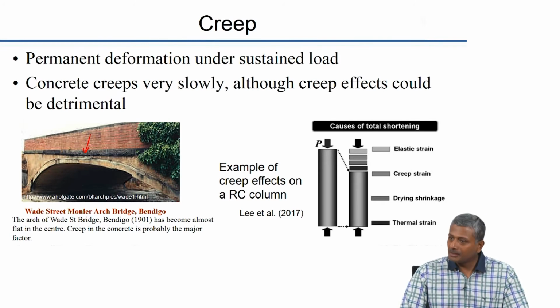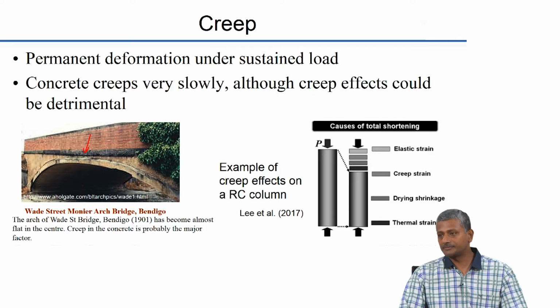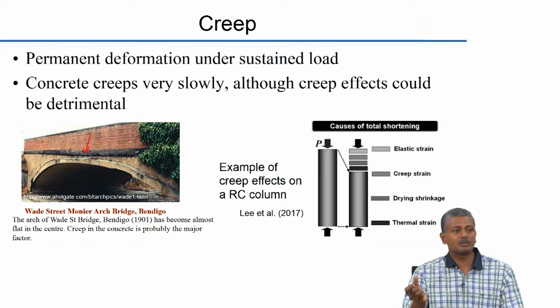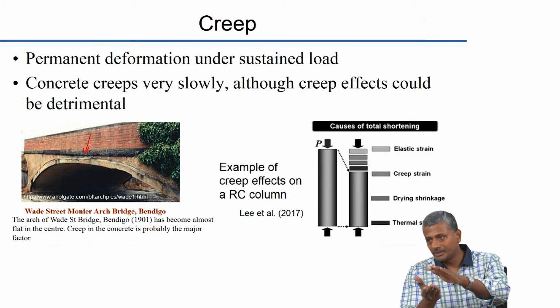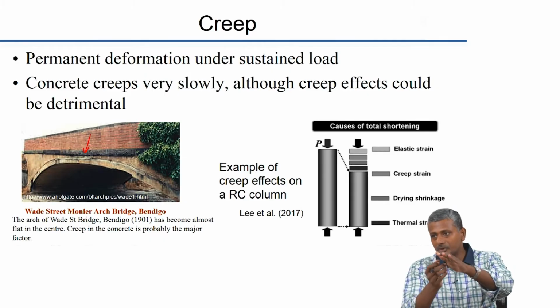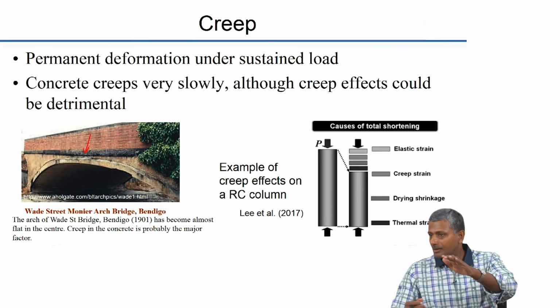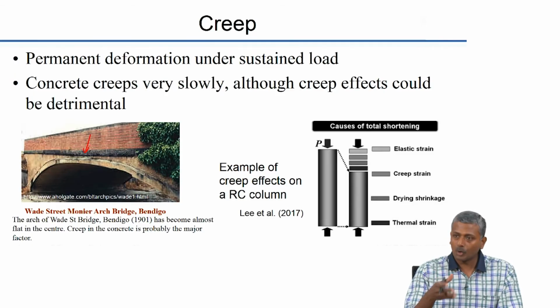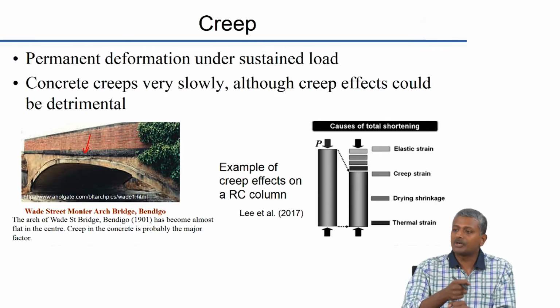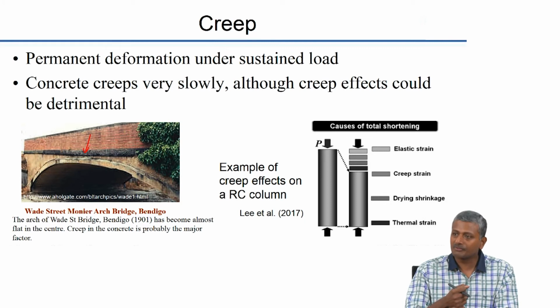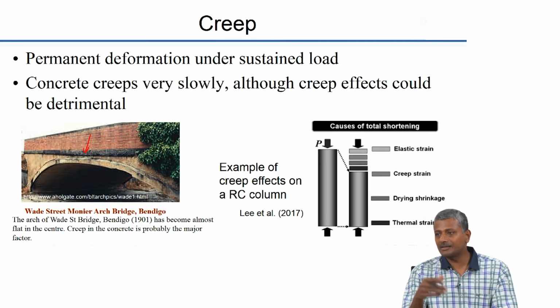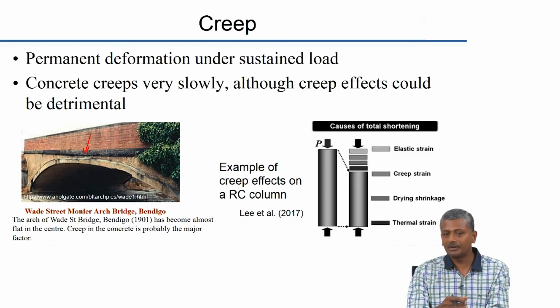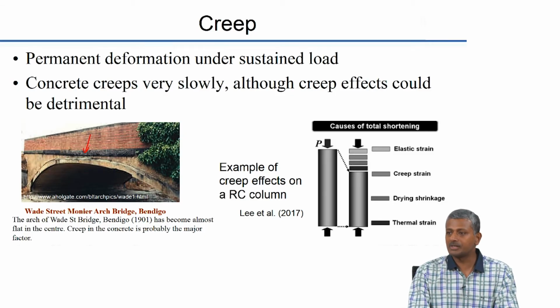So, creep in any material happens because of an internal rearrangement of the structure. In concrete, the internal rearrangement is primarily because of dissipation of water. For example, if you think about CSH, we talked about the Feldman-Sereda model, right? Water was present in different forms within the CSH. So, as consolidation happens, the layers of CSH will get closer together because this water starts dissipating to other areas, right. Similarly, in metals you have proper crystalline structure. With time the bonds will start getting strained, and because of creep you will have an internal rearrangement that will send the metal back to its lower energy state, right. So, again internal rearrangement of molecules leads to creep.